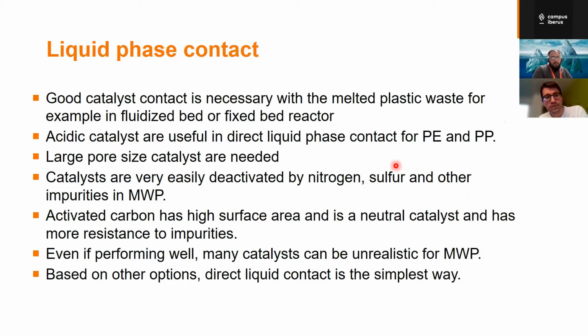Liquid phase contact. So this is giving you a bit more into how the catalyst can be used. In this one, good catalyst contact is necessary with the melted plastic waste, for example, in fluidized bed or in fixed bed. Acid catalysts are useful in direct liquid phase, for example, for polyethylene or polypropylene. Large pore size catalysts are needed for good cracking. But these catalysts are also prone to deactivation by impurities such as nitrogen, sulfur, or any other inorganic impurities that can be found in, for instance, municipal waste plastics. Activated carbon is one example which has a very high surface area and is a neutral catalyst and is more resistant to impurities. But in many cases, catalysts can be unrealistic, for example, for municipal waste plastic because it contains a lot of impurities.